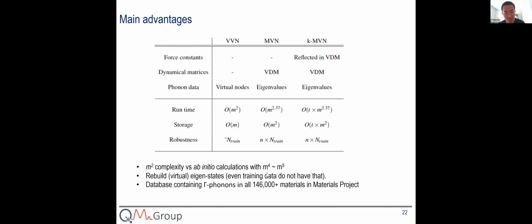To get an idea of the related computational costs compared to the ab initio approach: ab initio frozen phonon or DFPT approaches scale like m to the 4th to 5th order in the number of primitive unit cells. In our current approach, it roughly goes as m to the 2nd order, or less than m to the 2.5 order. That means that if you have 100 atoms per unit cell, it can reduce the cost by roughly 1 million times. We also tried 1,000 atoms per unit cell, and you can easily load them without having to go to a supercomputer.